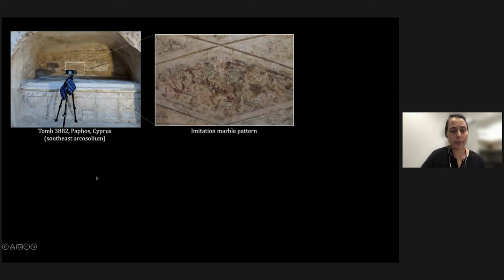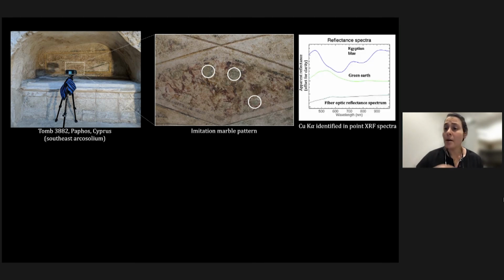So let me give you an example by this wall painting in a tomb in Paphos, Cyprus. And I'm focusing on a green paint on this wall painting. And I'll tell you right now, yes, it does have Egyptian blue. But if I look at the reflectance spectra from fiber optic diffuse reflectance spectroscopy, I can't see the characteristic triplet signature from Egyptian blue. I can only see that it's dominated by green earth, which is the bulk component of this green paint. When I look at the elemental spectra, I do see copper, but that's not enough because we know that there are other ancient pigments with copper in them.